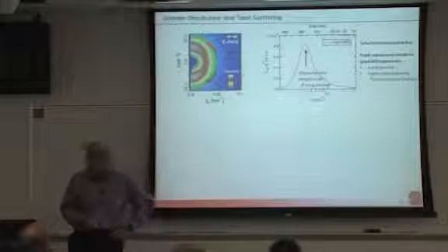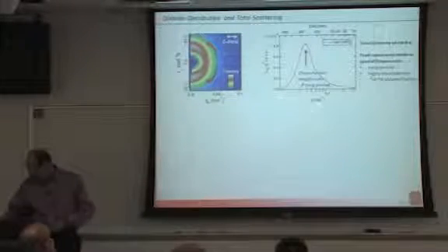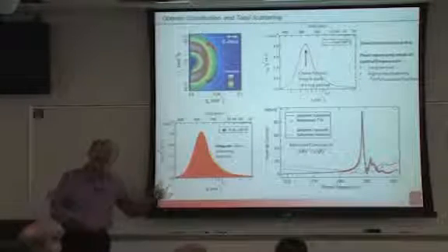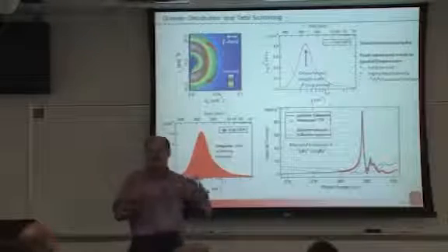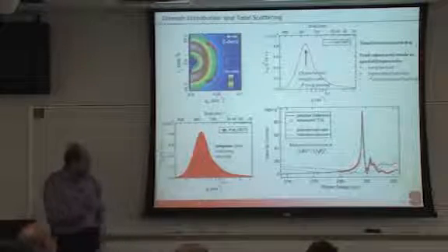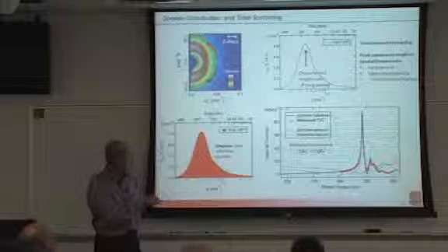So this is my total scattering intensity as a function of Q. So you see there's a distribution. There's a characteristic length scale, also referred to, if I translate that back into real space, as the long period. So that's fine. We can integrate this, and that goes back to what I said earlier. If I have just light gray and dark gray, I get less scattering than when I have black and white. So I can look at that total scattering intensity as a function of photon energy. And I can look at whether that follows the materials contrast or vacuum contrast or something else.